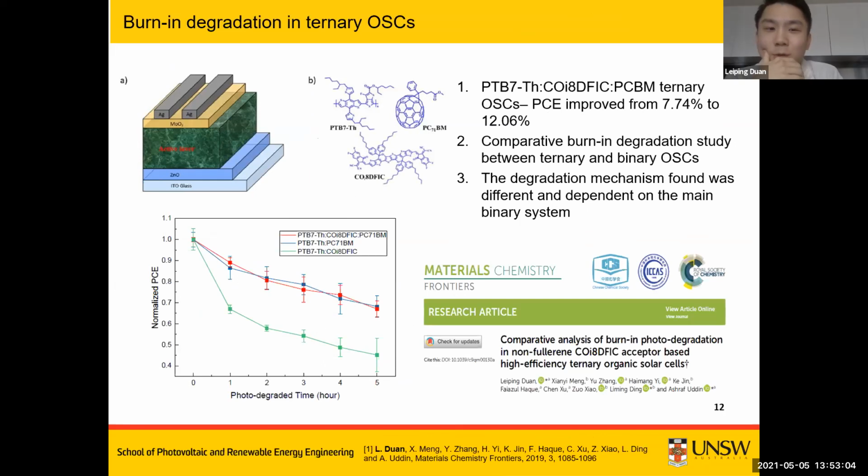Thank you for the question. First of all, for all the solar cells I mentioned here, the stability test was on unencapsulated devices. This is kind of a robust test; you can consider it an accelerated degradation test. I just put the cell under the solar simulator all day, so the light is continuous all day. But I do have experience in measuring encapsulated devices.